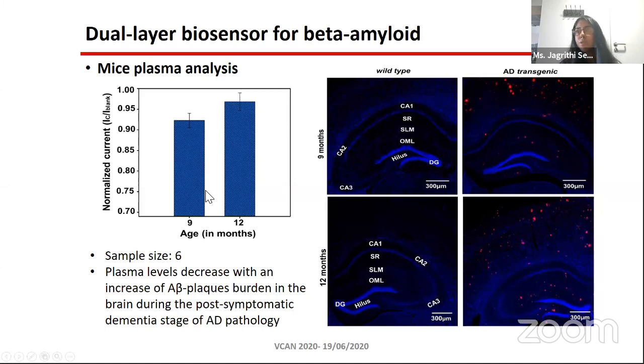So we took the samples from a 9-month-old transgenic mice and a 12-month-old transgenic mice. The sample size was around 6. And then with the biosensor, we can see that the normalized current shows an increase from age 9 to 12, which, estimated from our biosensor, means there is a decrease in the concentration.